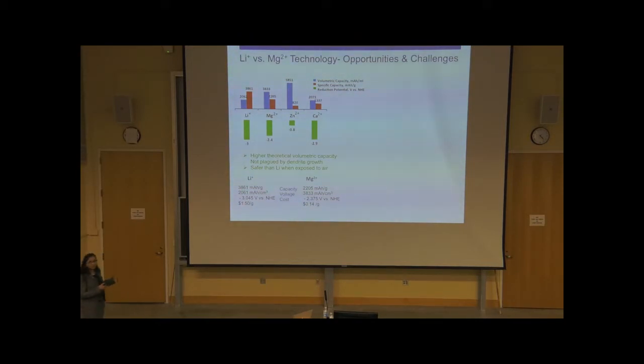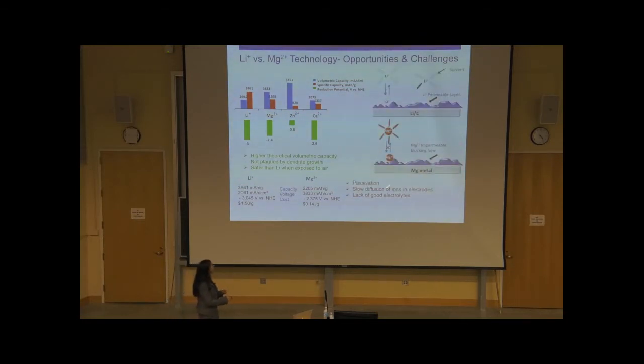All of these metals have their own advantages and disadvantages, but in particular, magnesium ion batteries have gained a lot of attention over the past several years because of their high capacity and much lower cost because of the high abundance of magnesium. But the commercialization of these magnesium batteries has several roadblocks. One of the major problems is the passivation layer formation on the magnesium metal surface. As I mentioned in the previous slide, in lithium batteries, we form this solid electrolyte interface, but it allows conduction of ions. That does not happen in magnesium batteries. So we form this truly impermeable blocking layer, which does not allow conduction of ions, which shuts down the battery.